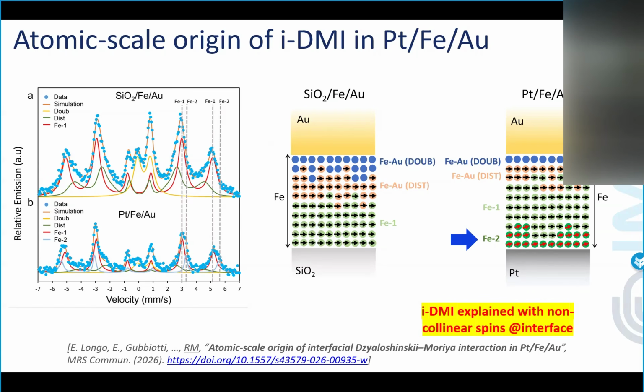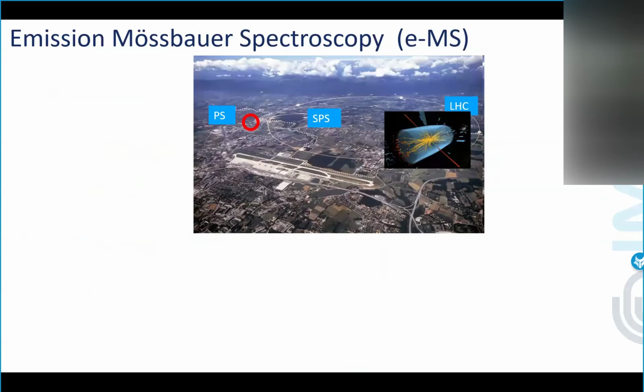So it was very nicely showing the Mössbauer spectroscopy that there could be some space for having perpendicular magnetic anisotropy and potentially skyrmion formation, even in relatively thick ferromagnetic materials. And now let's move to what was introduced already by Davide. The second part of the talk, I'll present some far less common strategy for making Mössbauer spectroscopy, in principle, in